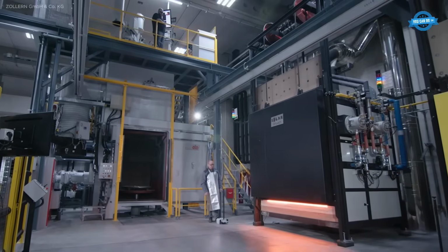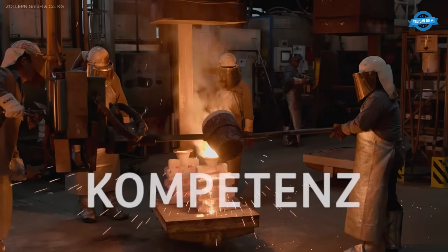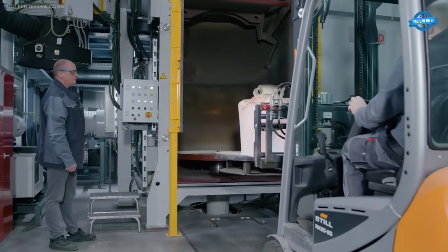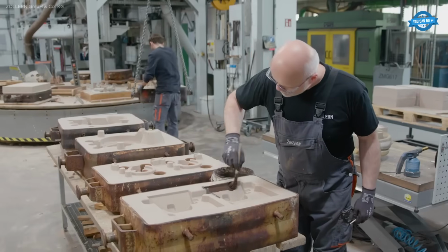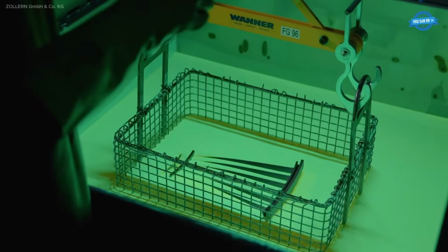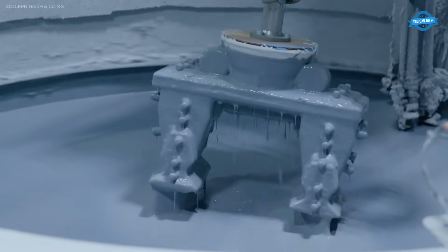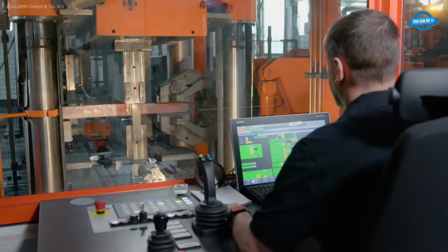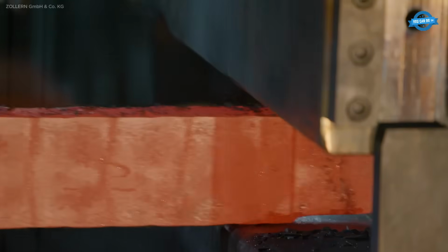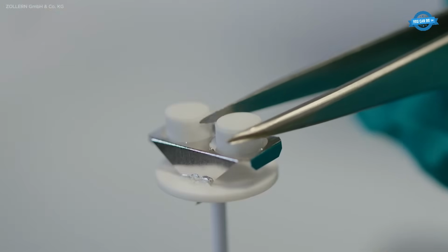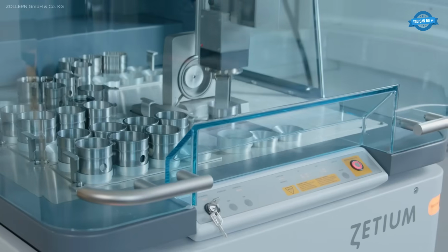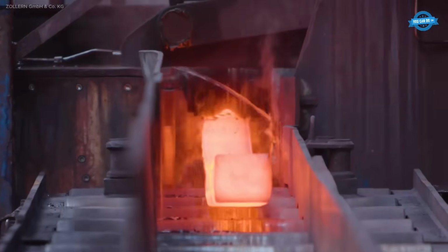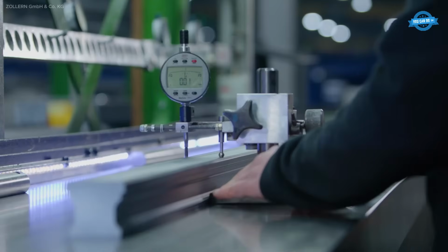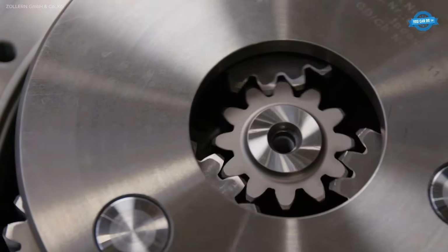Zollern's vertically integrated Laucherthal plant melts duplex, nickel-base, and copper-aluminium alloys in 4T induction furnaces, vacuum degassing and confirming chemistry via real-time spectrometry. Metal flows into 3 routes: centrifugal casting in 1,500 revolutions per minute copper molds for seamless rings with 1% wall variance, furan-bonded sand molds, MAGMASOFT optimized, bottom poured through ceramic filters for housings up to 15T, and lost wax shells de-waxed at 9 bars, poured under 10^-2 mbar vacuum yielding porosity-free turbo wheels.